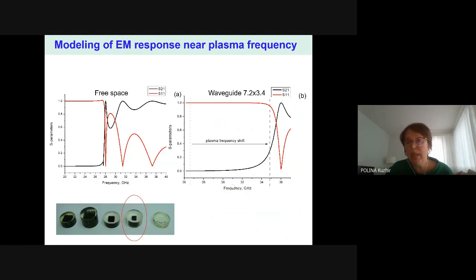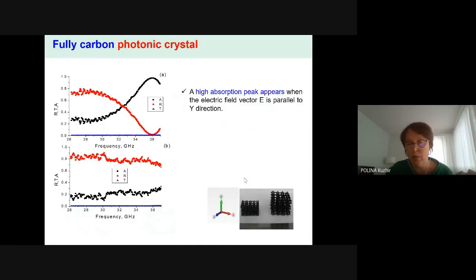Modeling says that at a certain frequency, called the plasma frequency, the behavior of this material could be fully changed from fully reflective to fully absorptive. And this is exactly what we observe experimentally for this particular cubic fully carbon lattice.